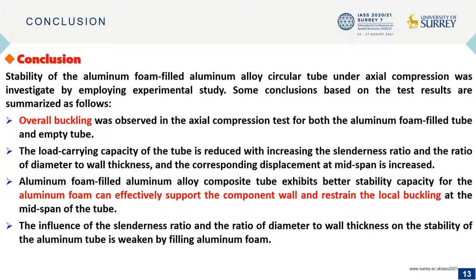Aluminum foam-filled aluminum alloy composite tubes exhibit better stability capacity, as the aluminum foam can effectively support the component wall and restrain local buckling at the mid-span of the tube.